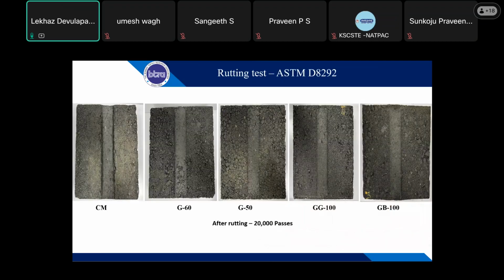So these are the images of the specimens. We can clearly see this one has a lot of rut, and there was also crack formation at the wheel path. When it comes to the other geogrids, like G60, G50, or the polyester grids with backing and without backing, and the glass grid with backing and without backing, the rut depth is almost 50% lesser than the control mix.